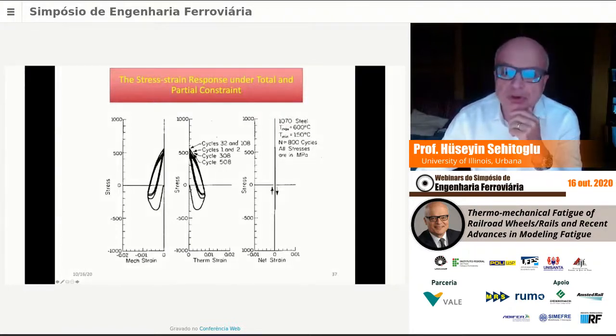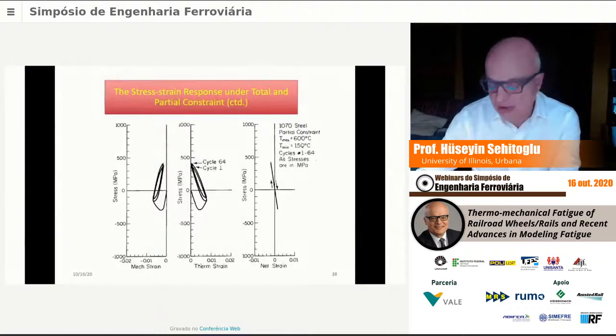This is the total constraint case, where the net strain is zero. You heat, you cool, you heat, you cool, and the mechanical strain is just equal and opposite to the thermal strain. When you heat, mechanical is negative and the stress goes up. As you keep increasing the temperature, the yield stress decreases with increasing temperature, so the stress strain curve has a curvature like this. Then the stress drops as you cool, and then you heat and cool again. This is between 150 and 600, for 1070 steel, the total constraint case.